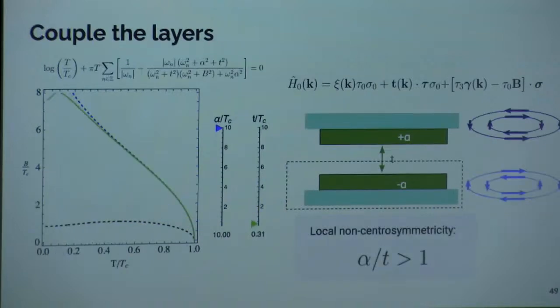Now we couple both layers, and now interlayer hopping couples two layers with opposite Rashba textures, so they cancel each other out. And this is why interlayer hopping suppresses the critical field. So there are now two important energy scales at play. One is spin-orbit coupling, which is alpha, and the other one is the interlayer hopping, which is t. As long as alpha over t is larger than 1, we can speak of reminiscent effects of a non-centrosymmetric superconductor, but in a globally inversion symmetric system.